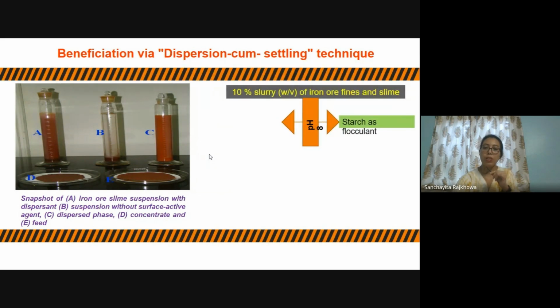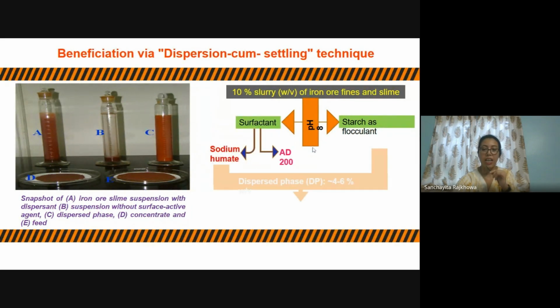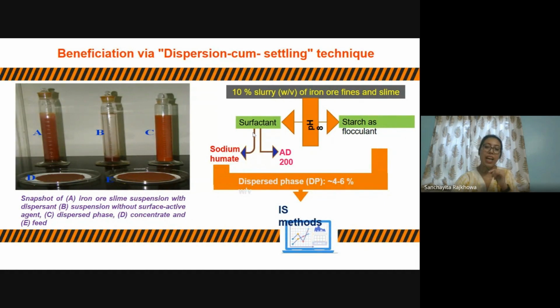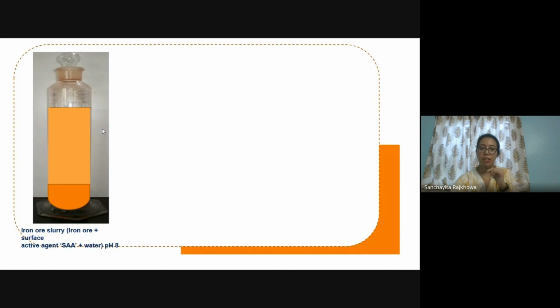Now, if we take 10% slurry, for example, and maintain the pH of the slurry at 8, and I will be talking about why pH 8, and if we add different surfactants, sodium humate and AD200, as well as starch as a flocculant, and if we take the dispersed phase, then it will recover 4 to 6% of the iron ore. And these ores, this dispersed phase, have been studied using different international standard methods, which I'll be discussing in the later slides.